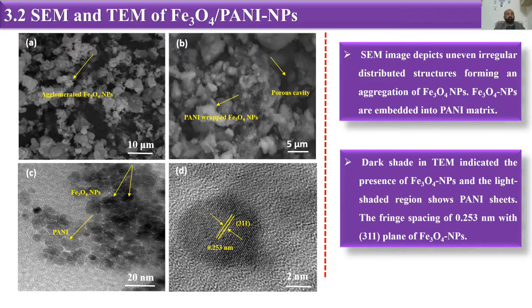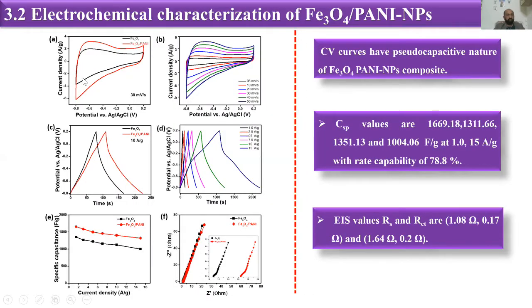Then we have done the electrochemical characterization again for our Fe3O4 composite, and we have got pseudocapacitive CV curves, which were also related to good capacitance. And then we have done the GCD for our Fe3O4 and Fe3O4/PANI nanoparticles, and we have got a specific capacitance of about 1669 and so on, and we have a capacity retention of 78.8%.